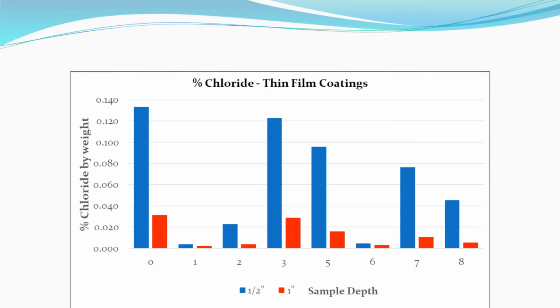You have 3 systems that gave you noticeably better performance than the other systems. Looking at color retention, I guess back up, the 3 systems here that show you the lowest chloride ion penetration, those are better than 90% reduction in chloride ion penetration.